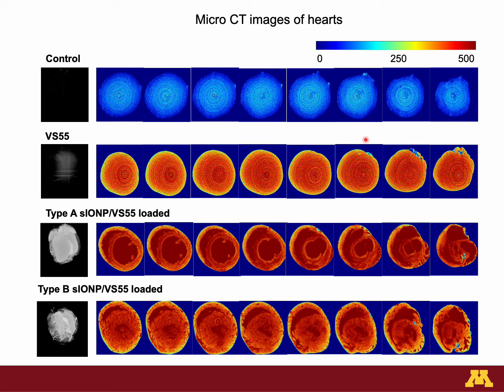The distension of the left ventricle and left atrium can be observed in the micro-CT image as you see on this slide. To quantify these dimensions, we analyzed the micro-CT images by creating a histogram of 50 axial cross-sections across the type A and B hearts, shown on the right side of this column. The left side of this column shows micro-CT images of the heart in Hounsfield units of 0 to 500, indicating the distribution of the heart. The micro-CT data showed the left ventricle and right ventricle distension in the type A cannulated hearts was greater than that of type B cannulated hearts. It leads to non-uniform loading and unloading of CPA and nanoparticles from the heart.